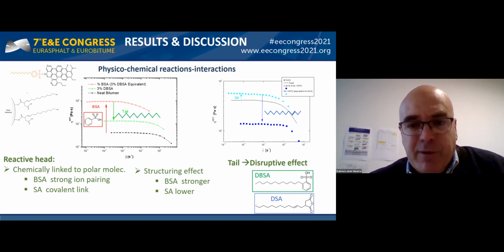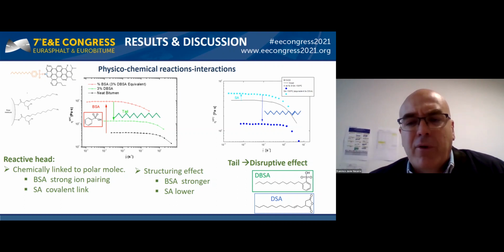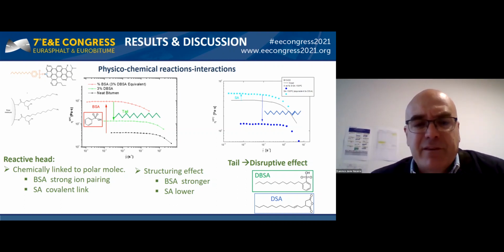On the other hand, according to the picture on the right, the individual addition of succinic anhydride only leads to a minor increase in viscosity. Therefore, taking into account that in this case, the modification is caused by the formation of covalent links having a much lower polarity, deformed structures are completely unable to promote the asphaltene aggregation. However, if we compare the modification caused by the polar head on both additives with those caused by the surfactant, it is clear that the presence of the aliphatic tail leads to a remarkable reduction in the viscosity. Therefore, this result confirms the previous assumption, and the attachment of the non-polar aliphatic chain clearly presents a disruptive effect.